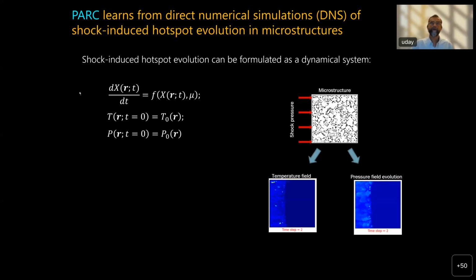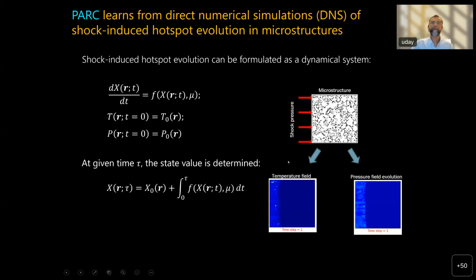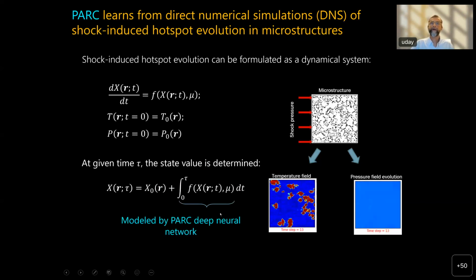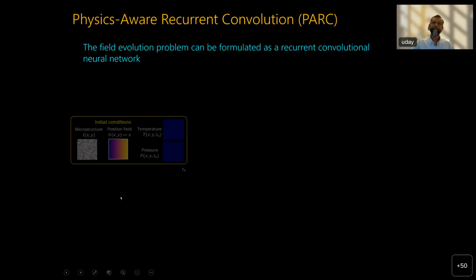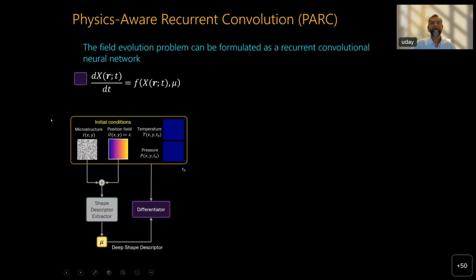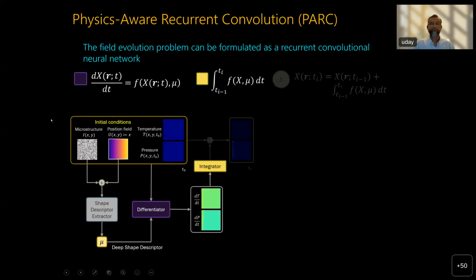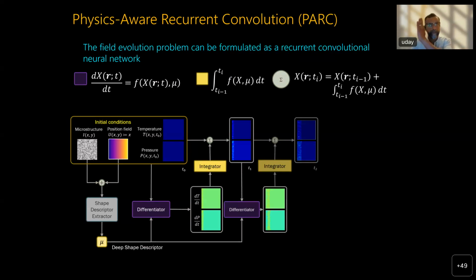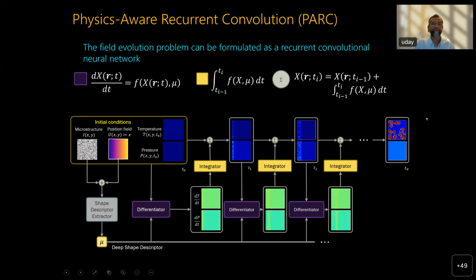So we want to track the evolution of all three things: the temperature, the pressure, and the microstructure. And so we train the model to learn the evolution of those three aspects from numerical simulations. And that's the idea behind PARC. So basically, PARC assimilates knowledge of how the evolution of this field x takes place. And we formulate it as a recurrent neural network where we have differentiator and integrator networks, and these differentiator and integrator networks assimilate the derivatives of the variable x, and then they perform the integration, and the time evolution is assimilated within PARC to eventually predict what happens at the end when the hotspots finally grow and merge in the material.